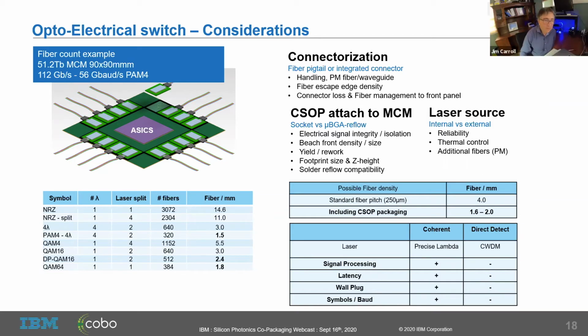Okay. Another thermal question: is the MT ferrule reflow compatible at 260C? And this refers to your 2019 Photonics West paper that our audience members saw. Yeah, we did a lot of work, but we don't have elite grade ferrules, so we only have more standard grade. And as we have seen, for example, the 1x8 ferrule was quite good, but when you try to do 1x12, the exterior fibers were a little bit worse. So no, the reflowable ferrules are not ready in the industry, not for the MT. There exists one for LC, but not for MT in single mode. That's the other thing, reflowable and single mode together.